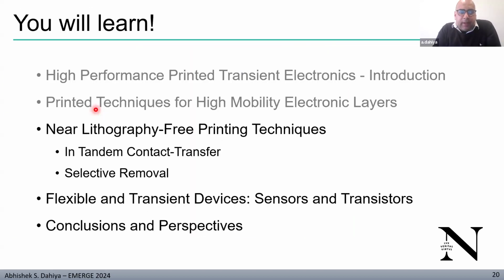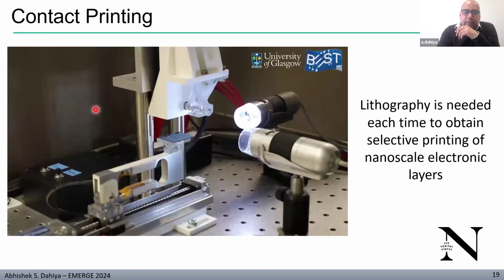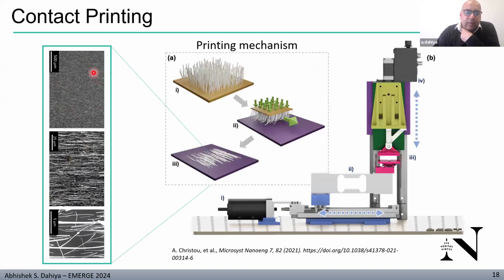Okay, so I have shown two techniques where we are using some kind of lithography technique to have a patterned electronic layer. For example, in the direct roll, we are using lithography each time while fabricating the nanostructures. And also for contact printing, if you want to have selective printing, for instance, here you can see that the electronic layer is everywhere. So if you want selective locations, you need to do lithography, and then you bring again the same process, you can carry it out, and the nanowires will be printed where there is an opening by the lithography that has been done.